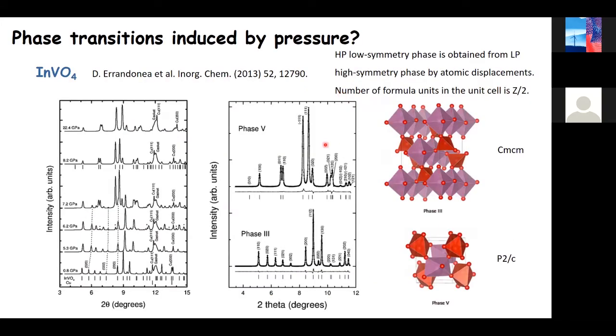Let me start talking about indium vanadate first. So for indium vanadate, we performed X-ray diffraction experiments. These are results from the X-ray diffraction experiment we did at the ALBA synchrotron in Barcelona. You can see here all the peaks. Most of them can be identified with the orthorhombic structure, which is this structure, the one we expected. We only have two other peaks: one is copper, which is our high pressure calibrant, and another broad peak, which is a reflection from the gasket we use to contain the sample. But in addition to these two, everything can be well explained by the well-known orthorhombic structure.